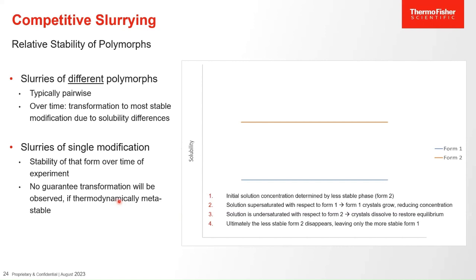Why is this? Well, in the mixed slurry, the concentration of the solution will be dominated by the less stable modification. Less stable modifications always have higher solubility than the more stable modifications. So this is down here. And this means that the solution is supersaturated with respect to the more stable modification, and the crystals start to grow. At the same time, if the crystals of the more stable modification grow, they reduce the concentration in solution, and as a result, the less stable phase responds by dissolving to restore equilibrium. And ultimately, after a period of time, only the most stable form is left.